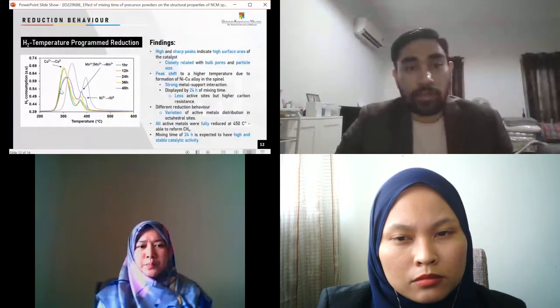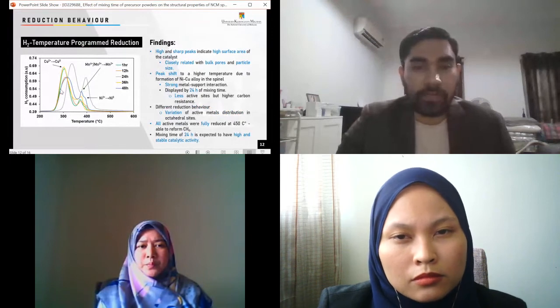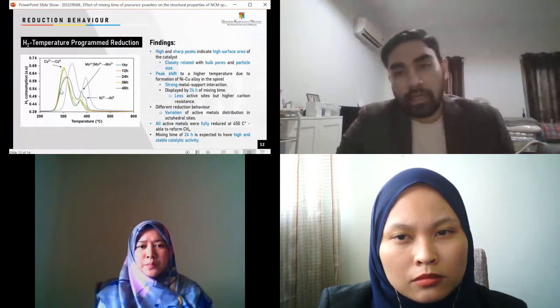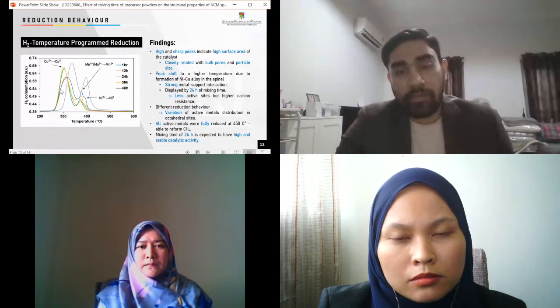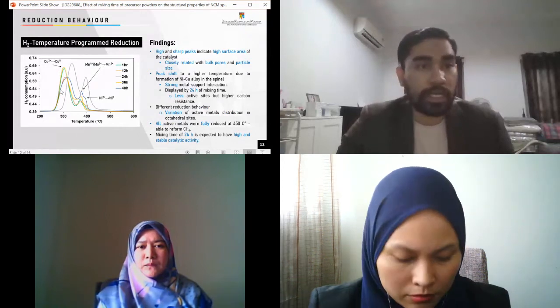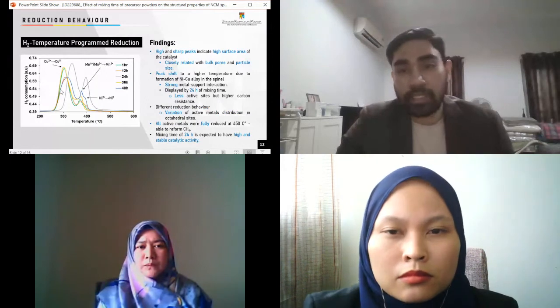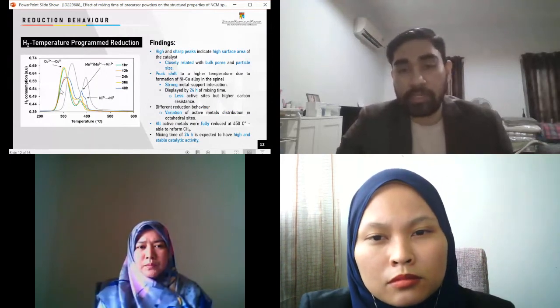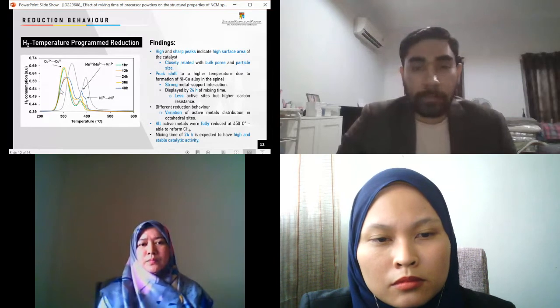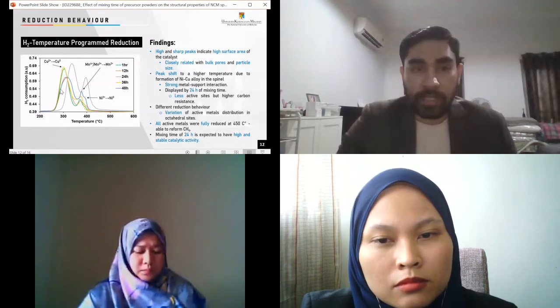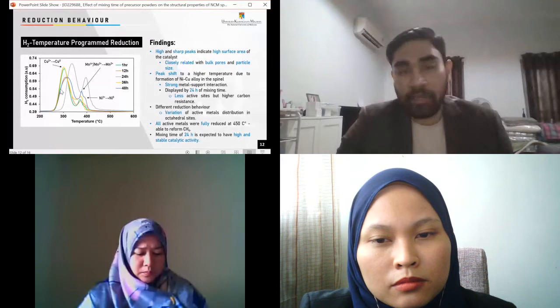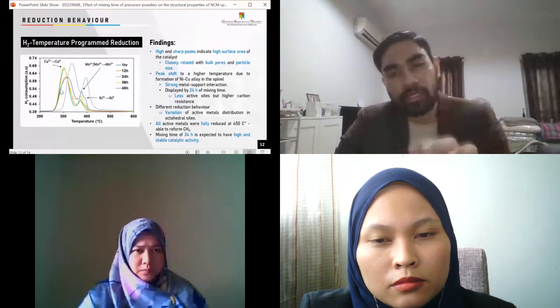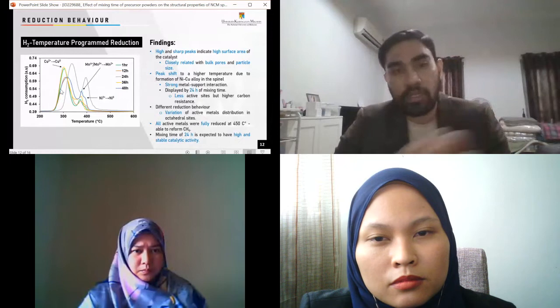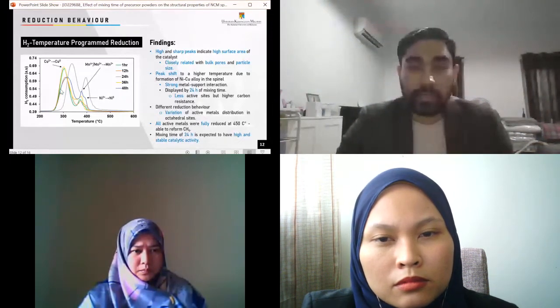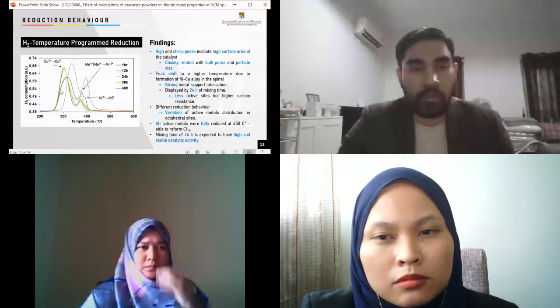Now, we can see that the difference in the structure can also affect the catalytic activity of the catalyst. Here I show you the hydrogen temperature programmed reduction, which is an effective analysis to determine the catalytic activity of each spinel, and this reduction behavior is closely related to its methane reforming performance. So the better the reduction behavior of the spinel, the higher the methane reforming performance expected.